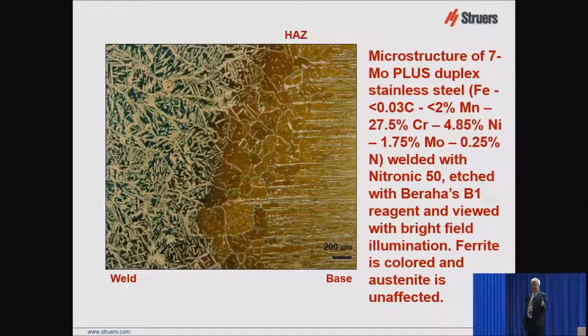Well, I know Carpenter's first effort to make a duplex stainless steel, they basically used 329 stainless and maybe modified it slightly, but it was 80% ferrite and only 20% austenite. And its properties were pathetic because it didn't stress corrosion crack, of course, but it wasn't ductile enough. So people have used adjustments to the composition of the austenite stabilizing elements to give you a little bit more than 50% ferrite and a little bit less than 50% austenite. That gives the ferrite the continuous path through the structure to prevent chloride ion stress corrosion cracking, but it doesn't destroy the mechanical properties. The duplex stainless steels have pretty decent properties.